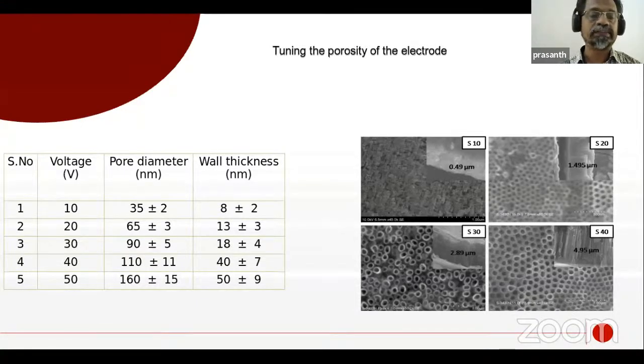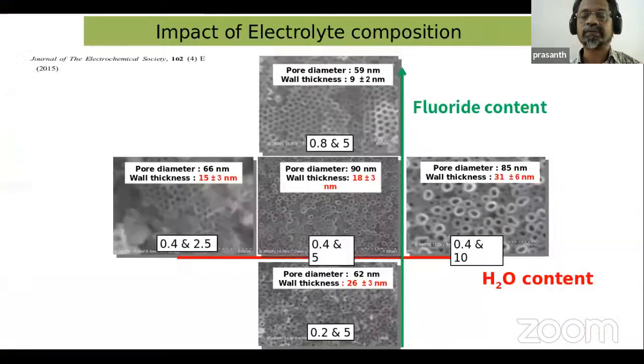So when you're playing with the voltage in electrochemical fabrication, you can change primarily the diameter of the tube, within some error. It is not a very accurate control you will get, but you can play with other electrochemical conditions also, so that you can understand what will happen with your structures. In the beginning of our research with TiO2 nanotubes, we played with many factors influencing the structure of TiO2 nanotubes. What is the impact of the electrolyte on the structural properties or morphology of the tube, and the growth rate of the tube, because different electrolyte compositions can give different growth rates of nanotubes.